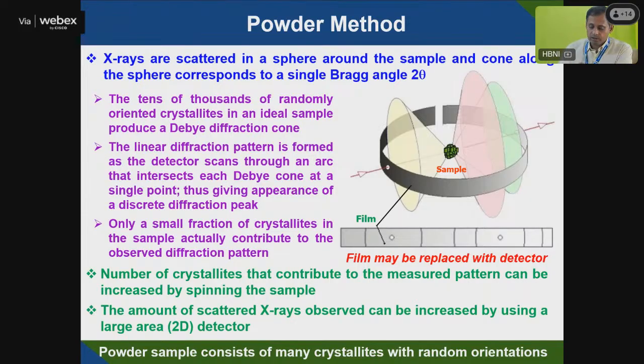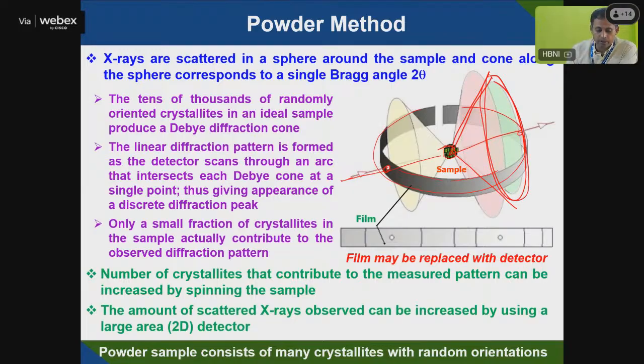So in the old days, we used this powder X-ray diffraction method using the Debye cone. There is a strip. On the strip, this is your sample here, and there is a thin film surrounding that sample. You can see that this is a very thin film, and there is a hole on this side. Your X-ray comes and falls on the sample, then it's scattered, then it diffracts. Depending upon the diffraction angle, you will be able to see a particular cone. This is called the Debye cone.